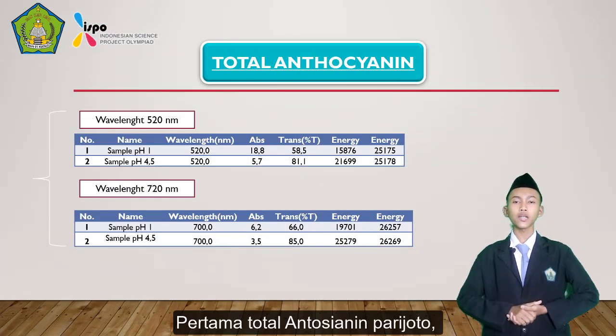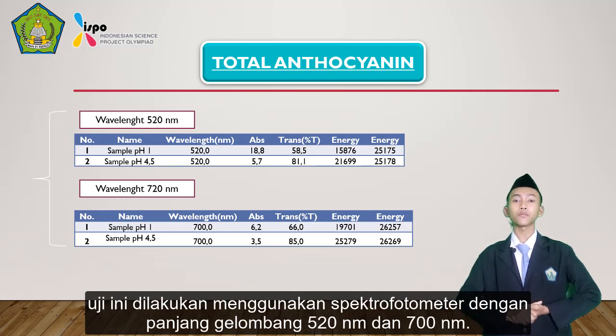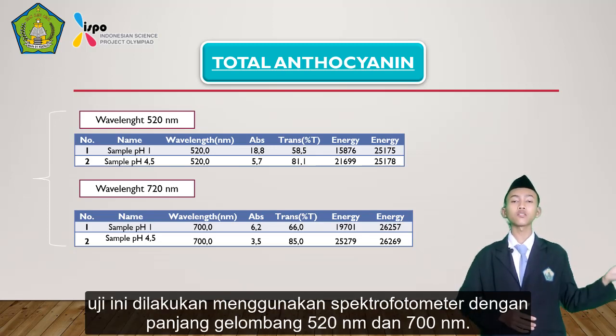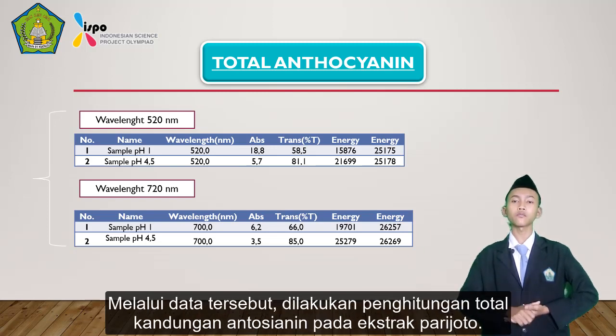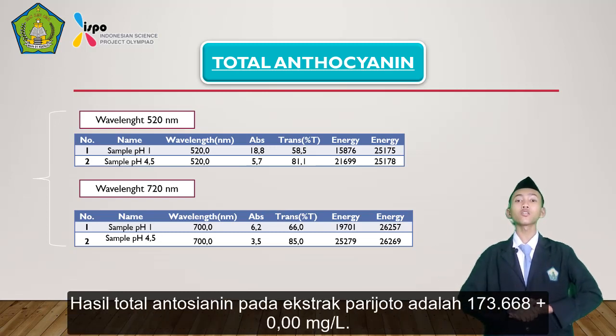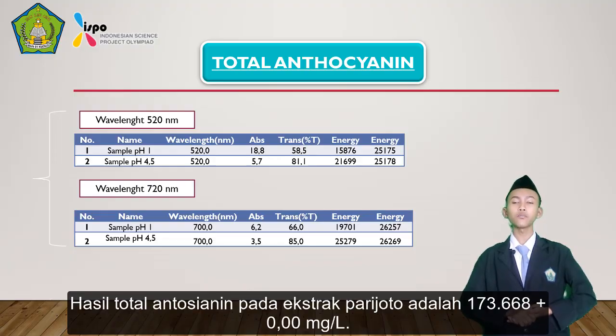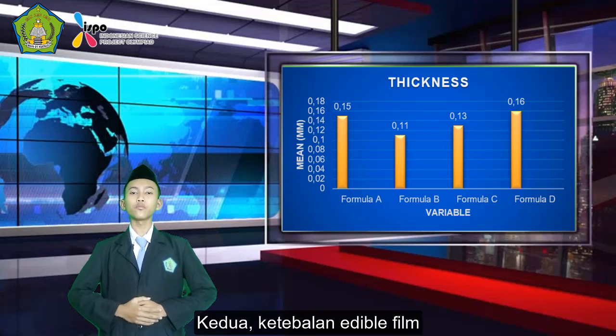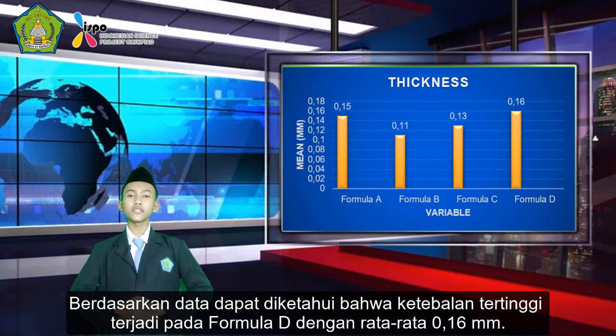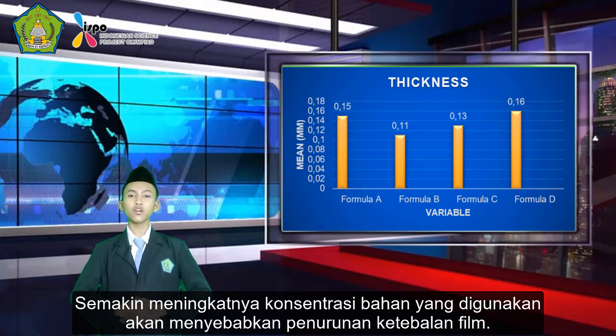First, the total anthocyanin parijoto. This test was carried out using a spectrophotometer with a wavelength of 520 nanometer and 700 nanometer. Through this data, the total anthocyanin content in parijoto was calculated. The total yield of anthocyanin in parijoto was 173,668 mg per liter. Second, the thickness of the edible film. Based on the data, it can be seen that the highest thickness was formula D with an average of 0.16 mm. The increasing concentration of the extract used will cause a decrease in the thickness of the film.